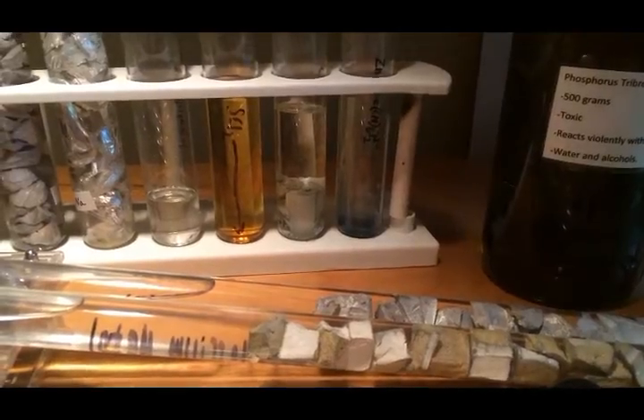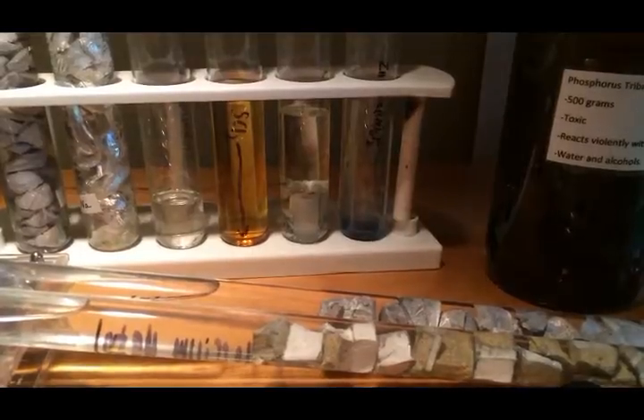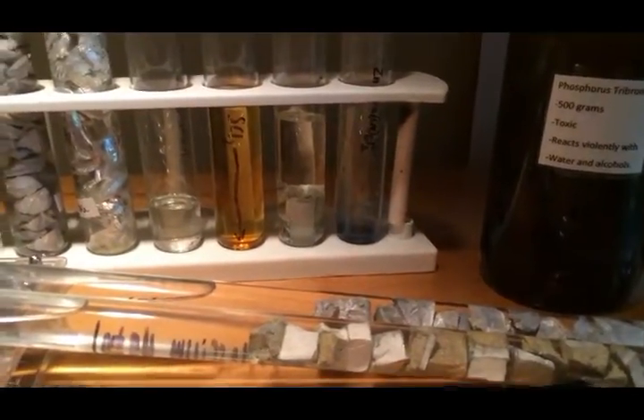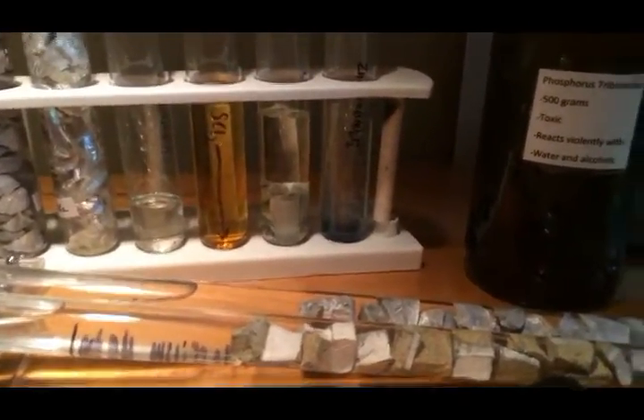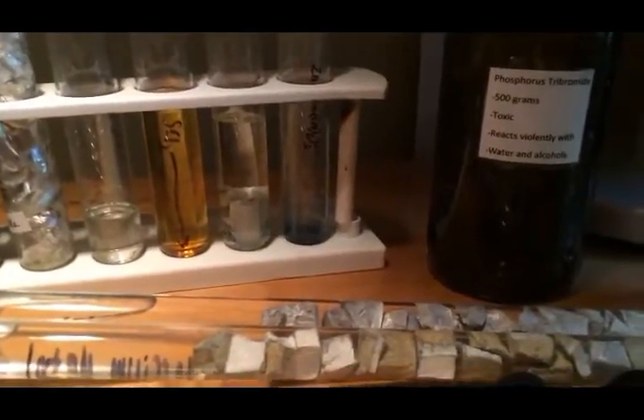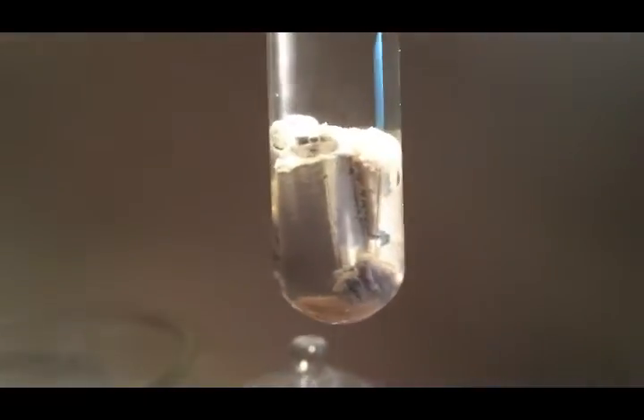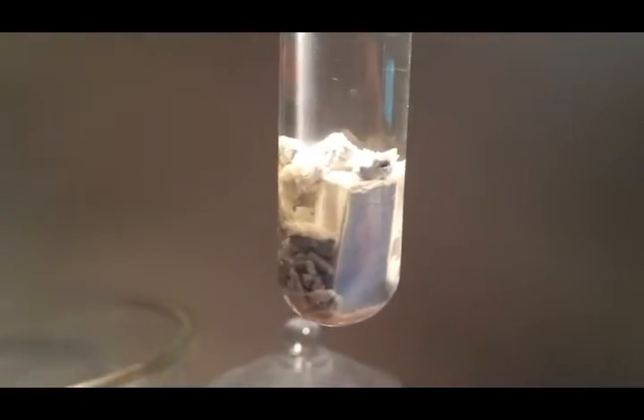To the right of the sulfur dichloride sample in this test tube rack is a strontium metal sample. And again, this one is interesting enough to warrant taking it out of the rack and getting a better view of it. At first, all it looks like is a bunch of heavily oxidized strontium metal under mineral spirits. But if you look closer, you might see that that piece in the front is unusually perfectly rectangular. And that's because I actually tried machining strontium once.